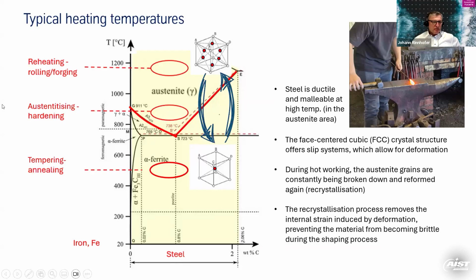What is very significant is the magic line around 900 degrees. So this is this red line where you come into the austenite area, and you can change the shape of the crystal, as we said in the beginning already, from body-centered into face-centered. This is why we always have to pass this magic line, the austenite line, for heat treating, for austenitizing and hardening, for example. And tempering can be at much lower temperatures because we don't necessarily change the crystal shape again.